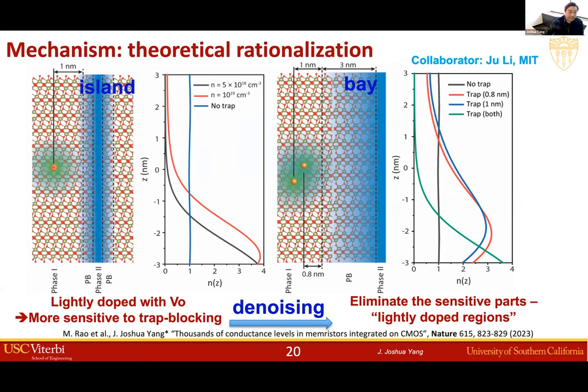And with a charge trap nearby to this incomplete channel, you can see, depending on the dopant level in the channel, if you have more oxygen vacancy like this one, then the channel can be partially blocked with the low resistance. But if you have relatively lower oxygen vacancy dopant in the channel, it can be fully blocked by this charge. And so this charge can come and go. That's why this channel gets blocked and unblocked, give us the RTN noise.